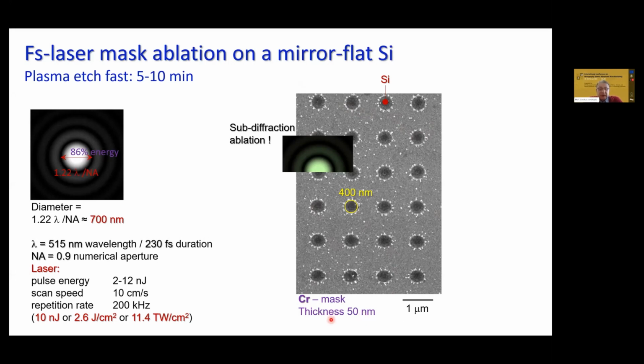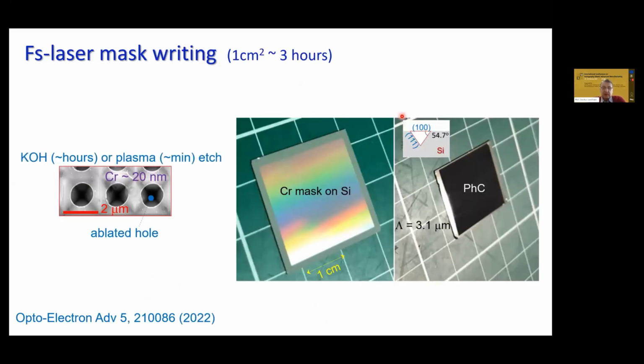It also can be dielectric. And we were writing single pulse ablation, driving at 10 centimeters per second. It could be faster. And at this rate, it was all perfectly aligned ablation patterns. And after you write the mask, you put your sample into wet or dry etching, into plasma. Plasma is much faster. In minutes, you can make all the surface into well-aligned photonic crystal.